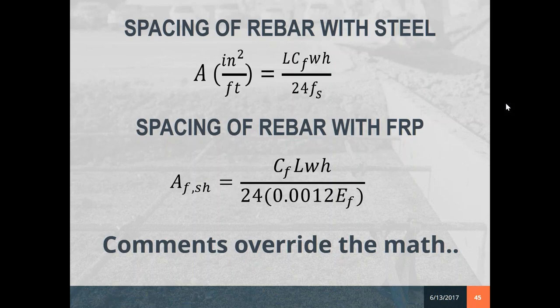They're built on different types of subgrades, more stable subgrades. Here in Houston, particularly, and across Texas, there are several locations where we have very expansive clays. Geotechs and engineers, being the conservative individuals that we are, will beef up this reinforcement in order to compensate for some of the movement of the subgrade. Again, if you have a really good compacted or stabilized subgrade, it reduces the shrink and swell of your subgrades. Therefore, you could reduce some of the reinforcement that's needed for your shrinkage and temperature control.